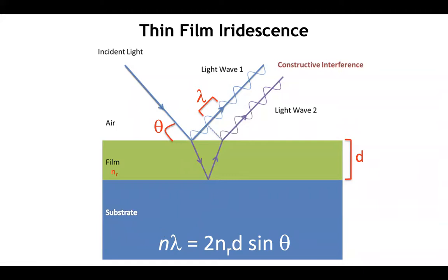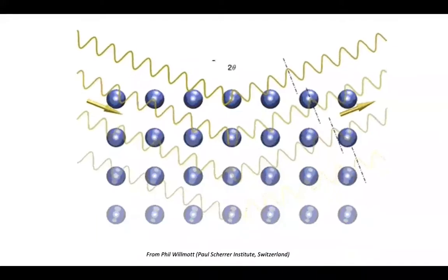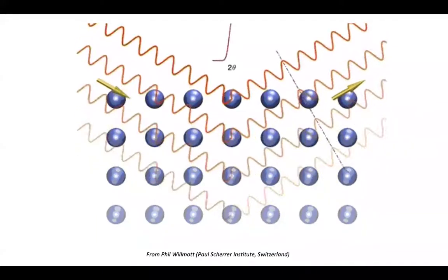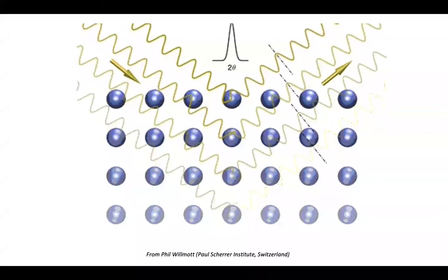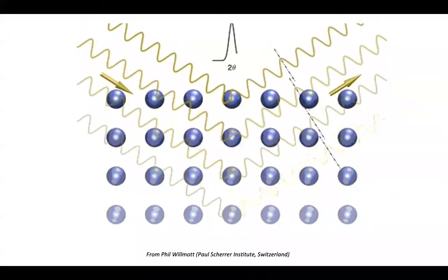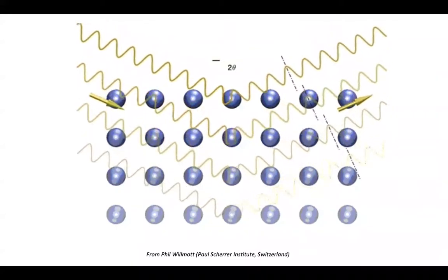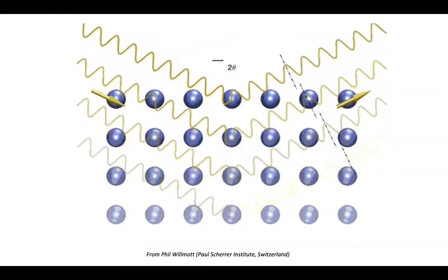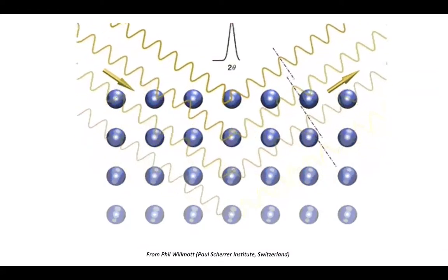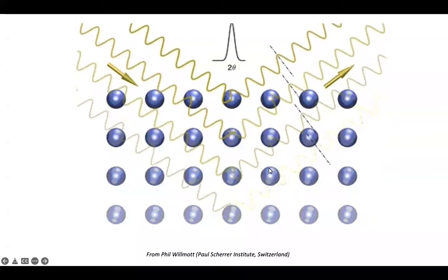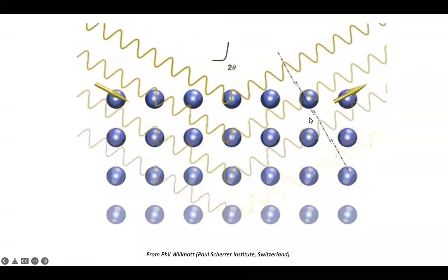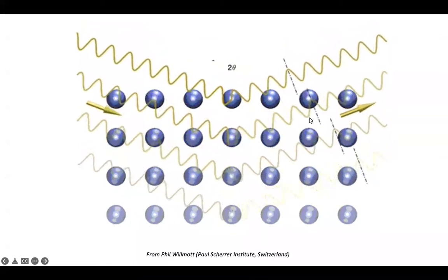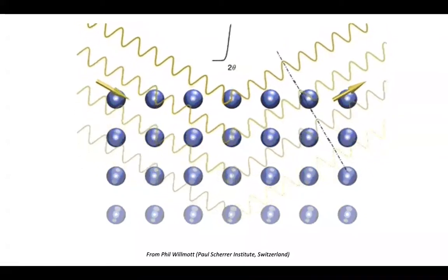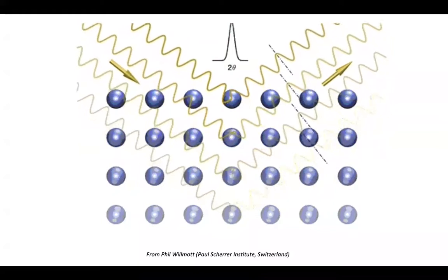When that condition is met, then we expect to see total constructive interference, and when it's not, it's going to achieve destructive interference. So that's illustrated in this animation that I purloined from the web, showing waves of a constant wavelength, lambda is not changing, interfering with a lattice with a constant d spacing, so the d is not changing. The only thing that's changing is the reflection angle right now. And you'll notice that there are moments when all of the peaks align at a particular angle, and we get that total constructive interference, but at all other angles, everything's going to cancel out, and it's destructive interference.